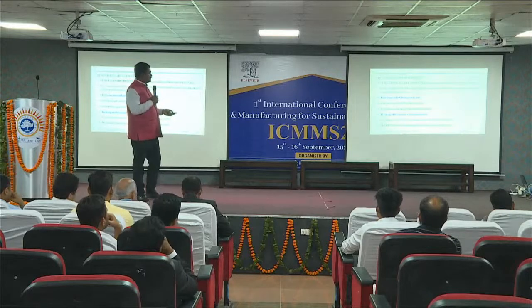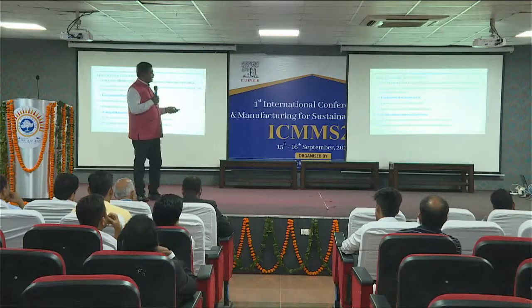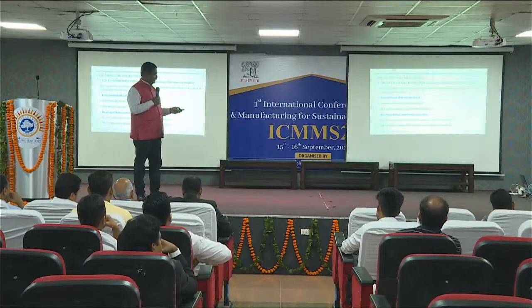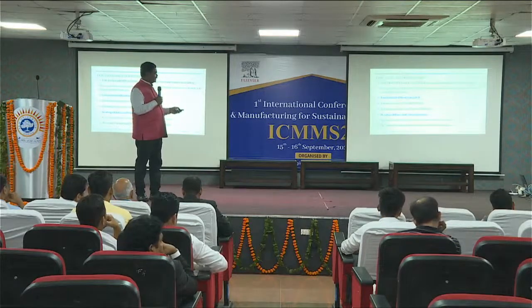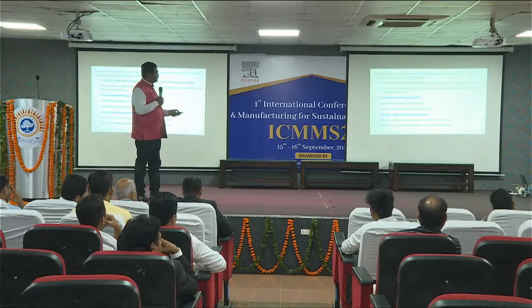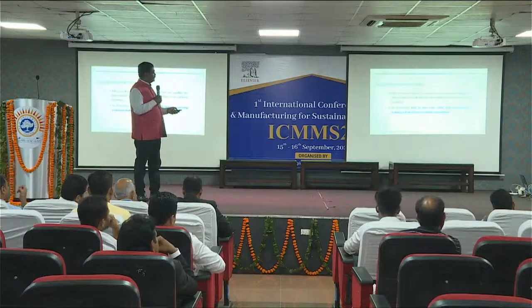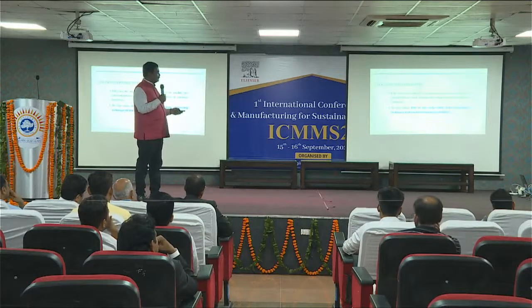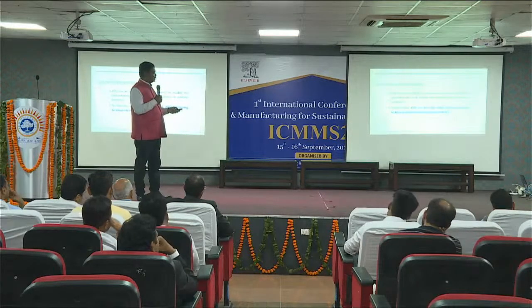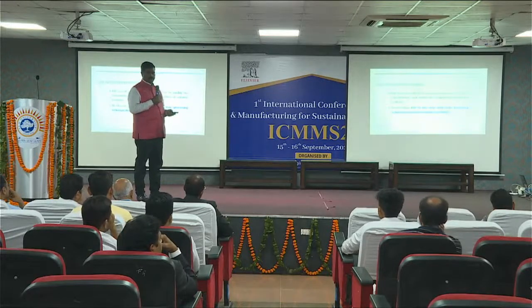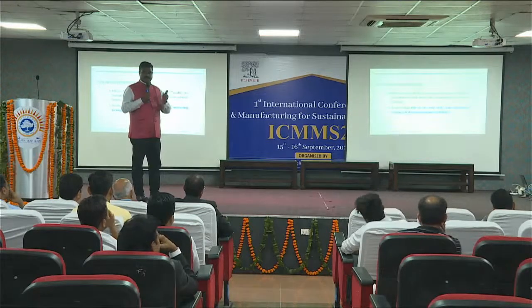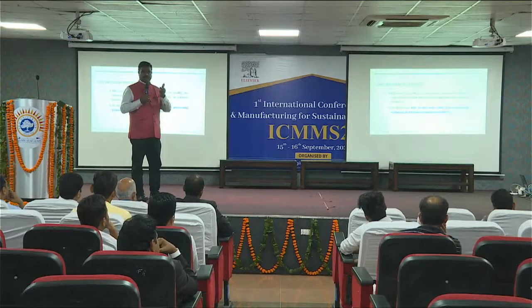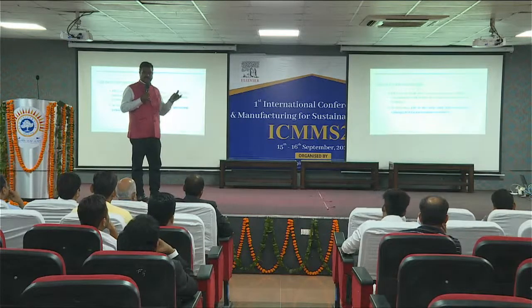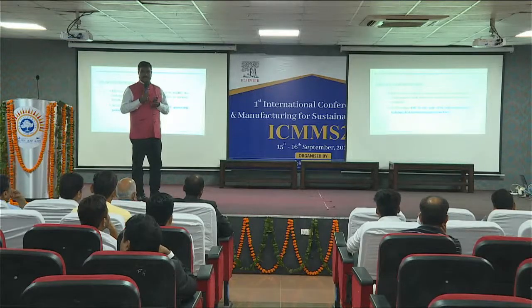So friction stir processing is an adaptation of friction stir welding. A low amount of heat is generated, there is healing of flaws and casting porosity, and this can be used as a generic process to modify the microstructure and change the composition by selective location. Selective location means, suppose wear and tear is there in some automobile parts, you concentrate on that, you adopt this technology, and you can strengthen the structure.